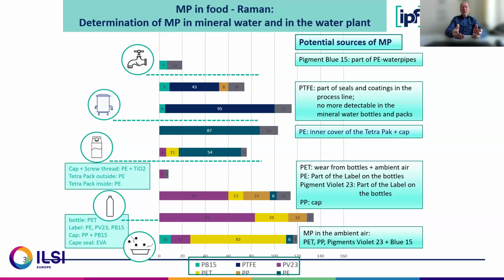And we sampled also the ambient air in this factory, and what we found is a lot of PET particles, and we found these PET particles then in the PET bottles also, because the particle size distribution for this PET in the ambient air was between 10 and 20 microns, and that same was also in the bottles. And then again, the pigments. It seems to be a greater problem that the pigments from the labels are in the bottles. What we also found here is that, depending, between 70 and 80% of the particles were below 20 microns. So we have only a very small amount above 20 microns. Most particles are below.